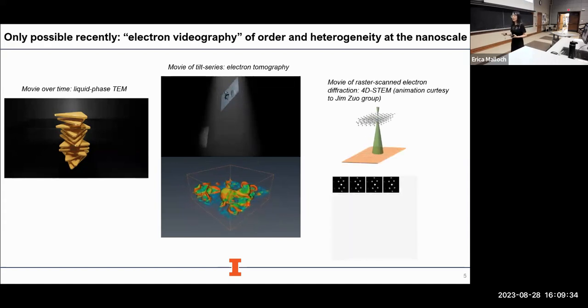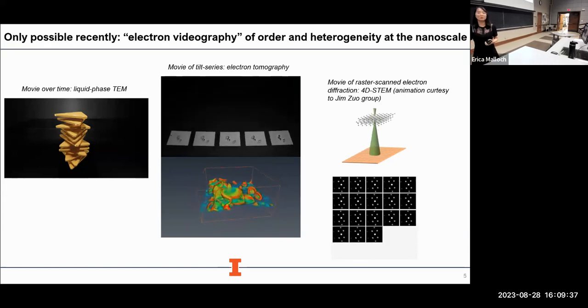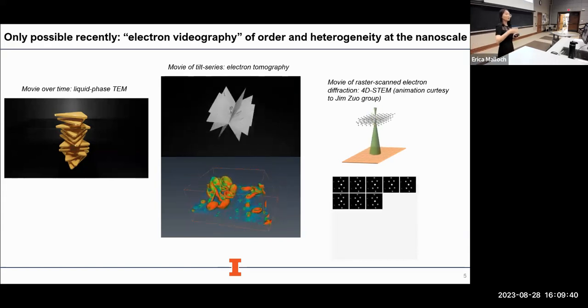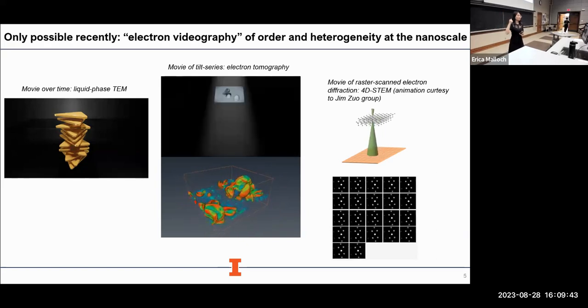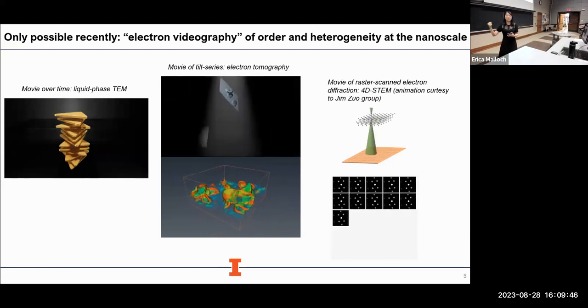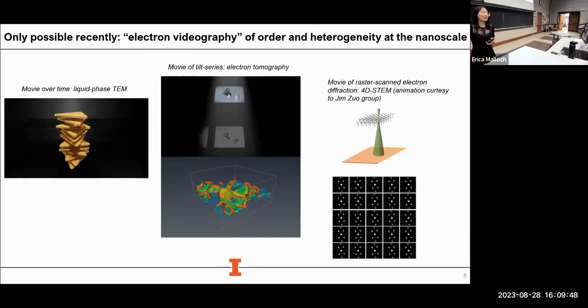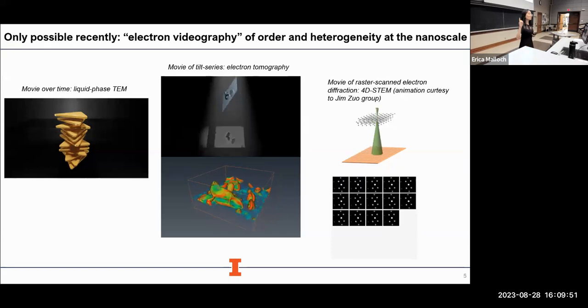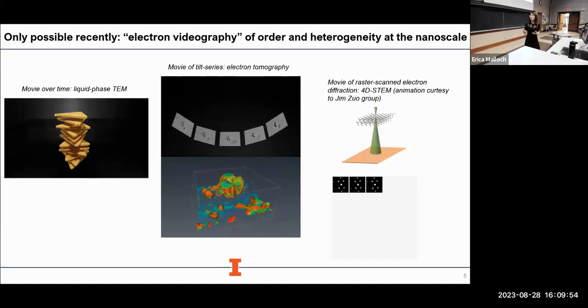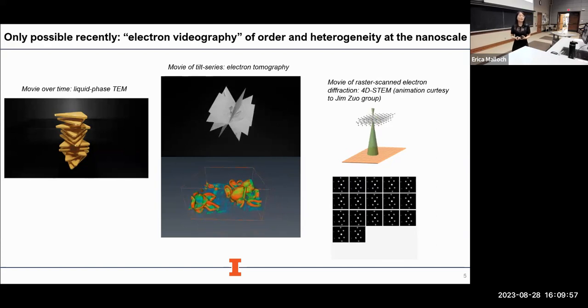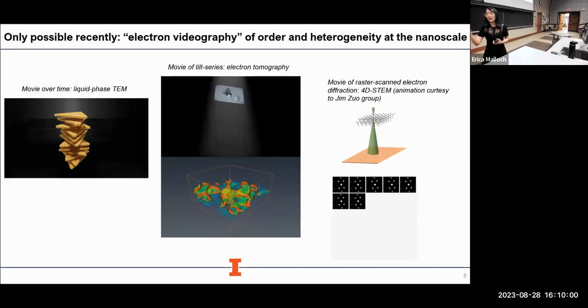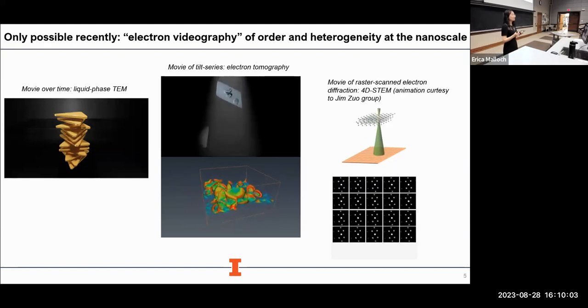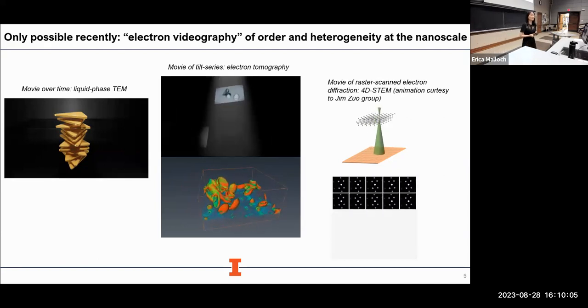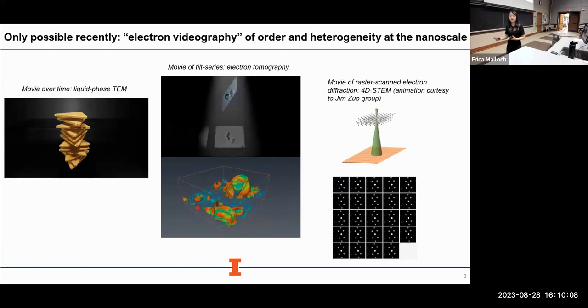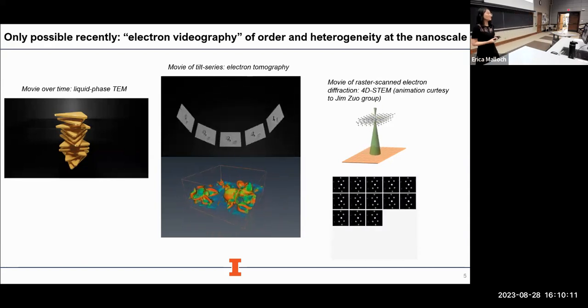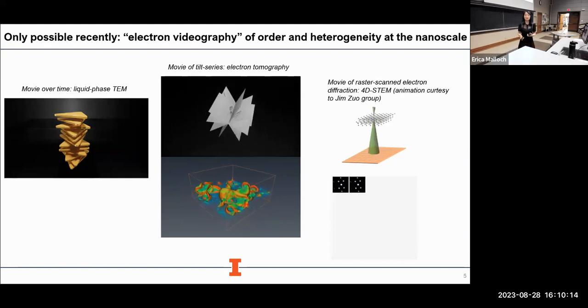Well, we can also have four-dimensional scanning transmission electron microscopy, or 4D-STEM. This is a technique that allows you to focus the electron beam into a nanometer-size probe. This electron beam can then interact with a nanometer-by-nanometer area of your sample, generating one electron diffraction pattern. And as shown beautifully in this animation made by Jim Zuo's group, you can then raster scan this electron beam probe to collect a two-dimensional array of electron diffraction patterns. From those patterns, you can map out the phase, orientation, and strain at otherwise inaccessible nanometer resolution.